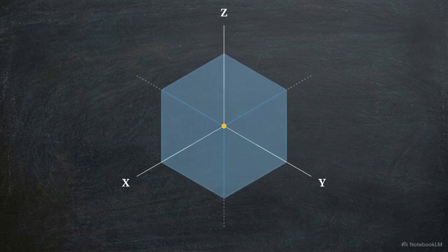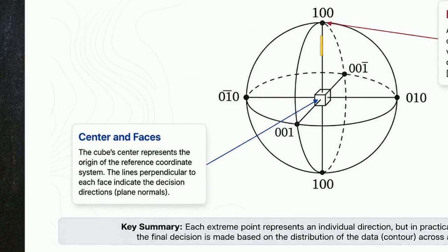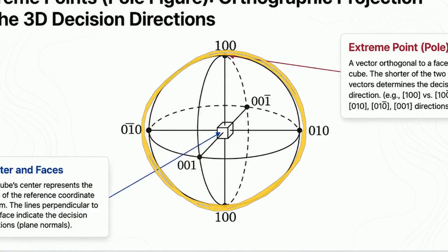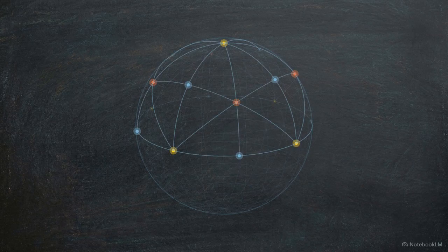The geometry begins by isolating a single cubic unit cell at the exact center of a 3D coordinate system. This schematic isolates a central unit cell and defines its direction, a vector extending perpendicular from a crystal face. To map it, we enclose the cell within a perfect reference sphere. The intersection where that vector pierces the surface is the pole. By tracking the coordinates of these extreme points, we establish a reliable framework to plot the crystal's spatial orientation.